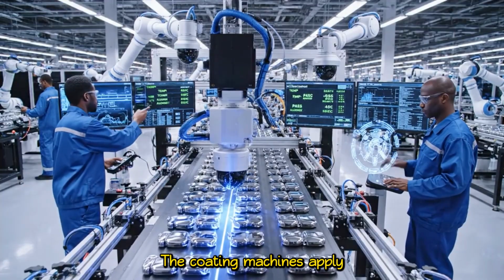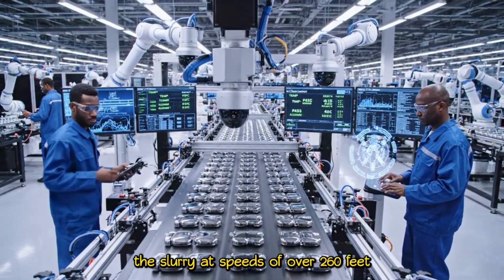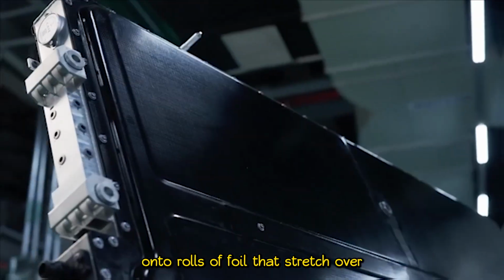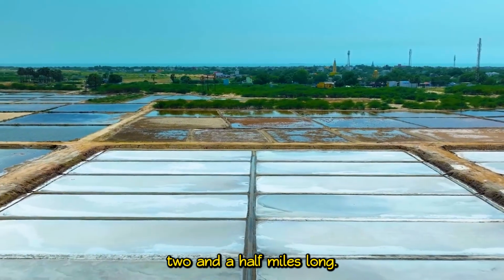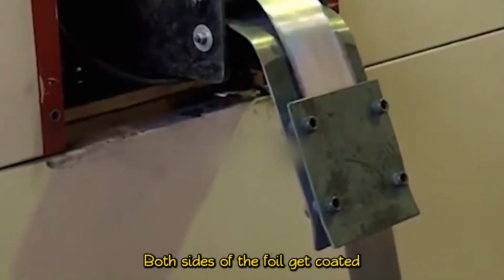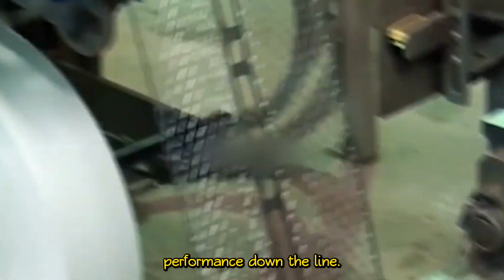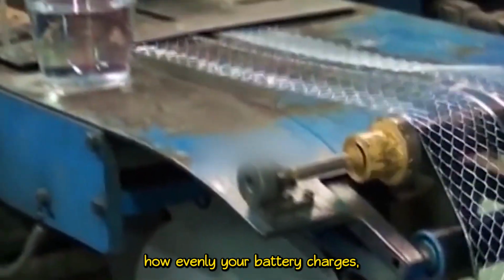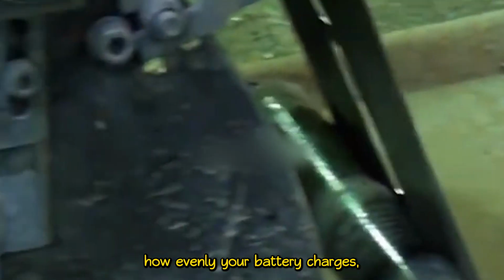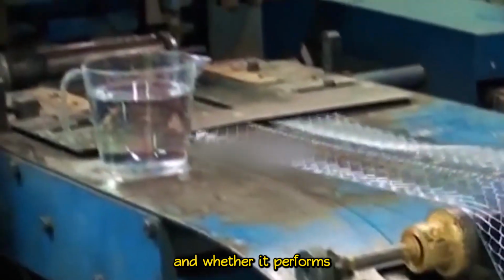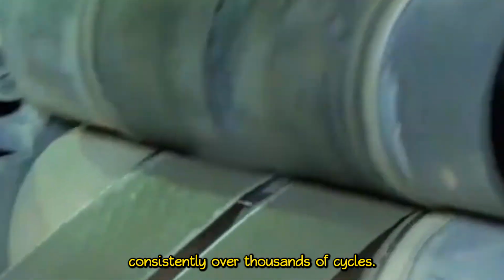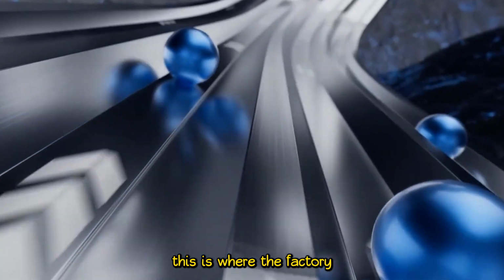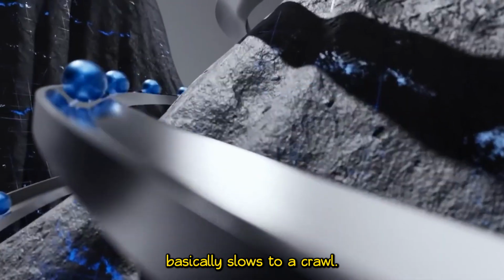The coating machines apply the slurry at speeds of over 260 feet per minute onto rolls of foil that stretch over 2.5 miles long. Both sides of the foil get coated with microscopic precision, and any unevenness, even a fraction of a micron, could ruin the cell's performance down the line. This single step determines how evenly your battery charges, how long it lasts, and whether it performs consistently over thousands of cycles. But the next part, this is where the factory basically slows to a crawl.